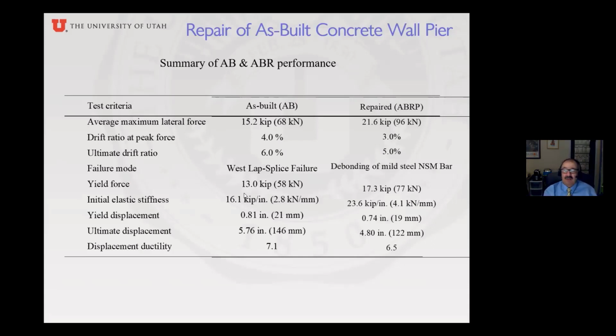Yield force was roughly the same. Stiffness was much stiffer for the repair one. Yield displacement about the same. Ultimate displacement a little bit less for the repair. And the ductility, which is the ratio of the ultimate to the yield, was 7 here and was 6.5 for the repair. But to give you an idea, 6.5 is not bad. For example, Caltrans doesn't want you to design something with more than 5. So 6.5 is good.